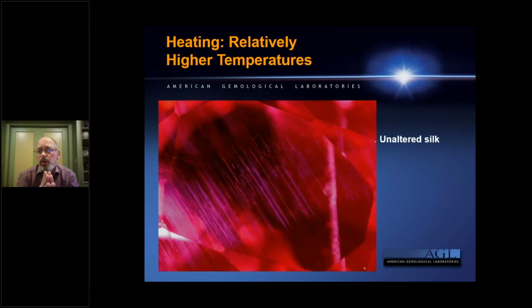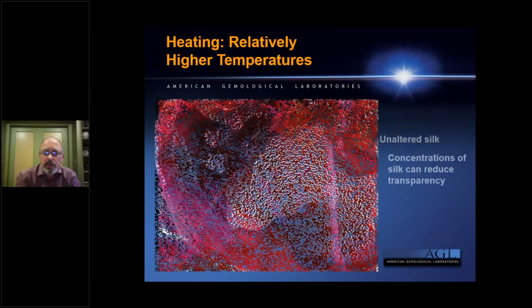So again, here we're talking about dissolving above the threshold to dissolve rutile silk. Here's a ruby that has very fine inclusions of rutile silk. This is quite sparse. It's actually a pretty picture to see when you're looking at it with a loupe or with a microscope, but this is not the kind of stone which you're going to want to heat to dissolve the rutile silk. What you also can have happen are stones such as this.